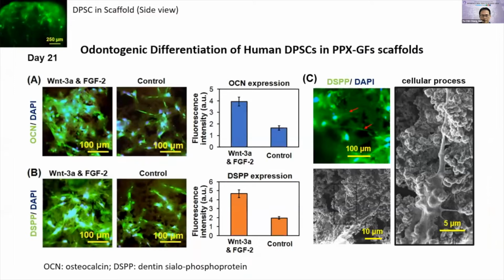And in this slide, in the left-hand side corner, we can clearly see dental pulp stem cells grew into the PPX scaffold. In addition, we also studied the effect of dental pulp stem cell differentiation on growth factor contained PPX. We found that they significantly increase both OCN and DSPP expression. It is speculated the PPX with such growth factors has very high potential to encourage the dental pulp stem cells to differentiate into odontoblasts.